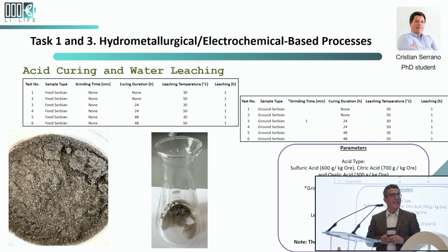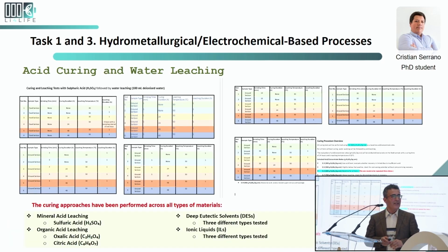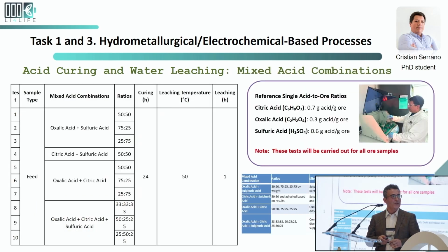We also use the acid curing, and we have already obtained interesting results, which significantly help in order to avoid going close to 1,000 degrees. You can do it in ambient or maximum up to 200 degrees. These are our experimental setups, so I don't want to bother you too much.